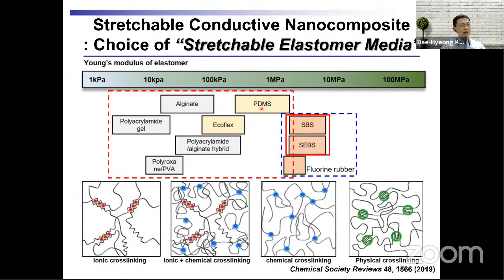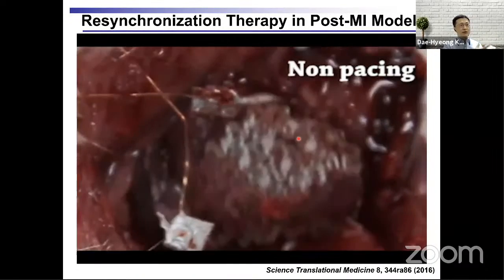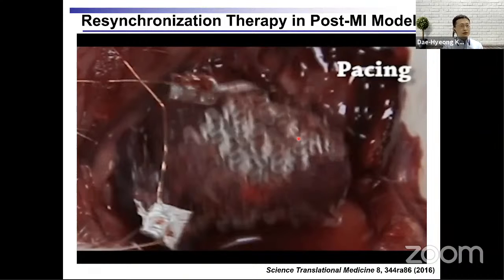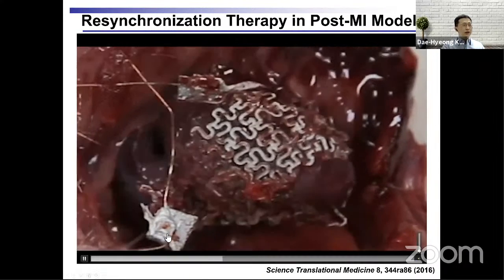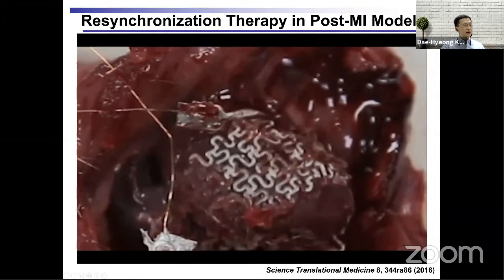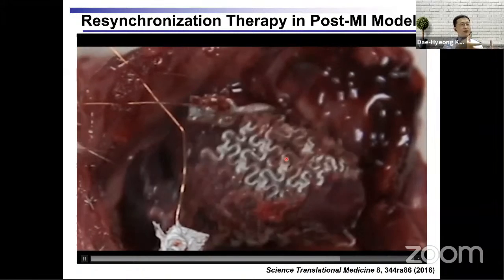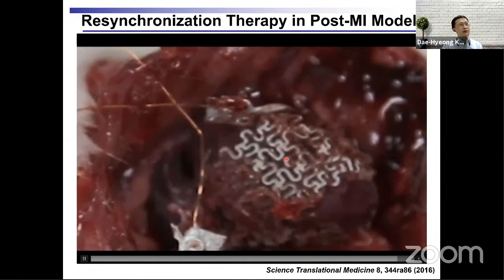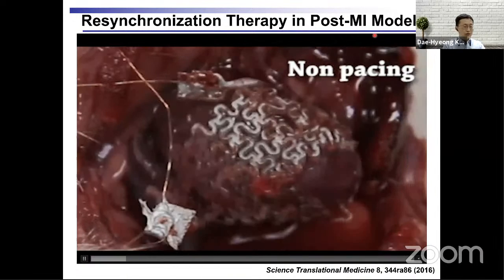So there is a limitation in increasing the loading amount of the conductive filler in the case of chemically cross-linked polymers. So instead, we used thermoplastic polymers. In these cases, as long as we can apply appropriate heat, we can proceed with the polymerization, even though the loading amount of the conductive fillers is high. So by using the thermoplastic elastomers and ultra-long silver nanowires, we fabricated this cardiac mesh that wraps around the animal heart, which is a post-myocardial infarction model, and restored the normal heartbeat.